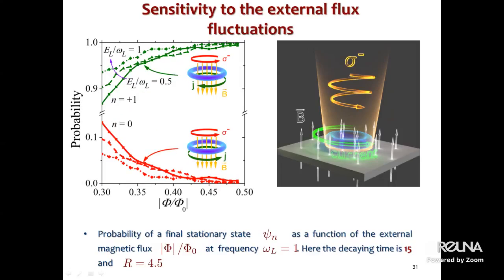Next, we need to demonstrate the sensitivity of the switching effect to the external flux fluctuations. Here I present the influence of the amplitude of the applied DC magnetic field, or DC magnetic flux, and how it influences the probability. It's clear that the probability of reaching the desired final state is already close to unity when the flux is larger than, let's say, 0.45.